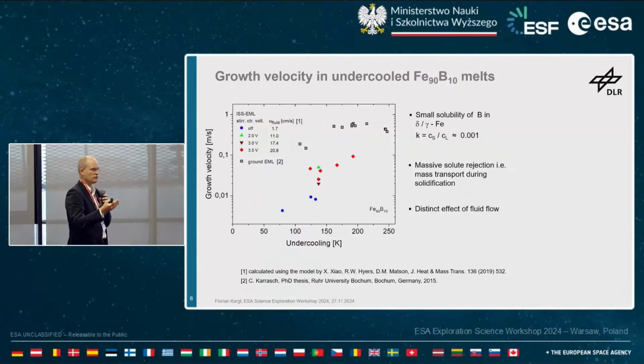So you have diffusive transport of the iron to the interface, and you have diffusive transport of the boron away from the interface. And that restricts pretty much the growth velocities. If you do that on ground, you have strong stirring. This is the data up here. You have 2 orders of magnitude higher growth velocities at similar undercoolings. And this is simply because due to convection, you're transporting a lot of iron to the interface. And then you can see here nicely in between, when you vary fluid flow conditions, you end up with the growth velocity somewhere in between the ground-based data and data where you have low fluid flow in space.